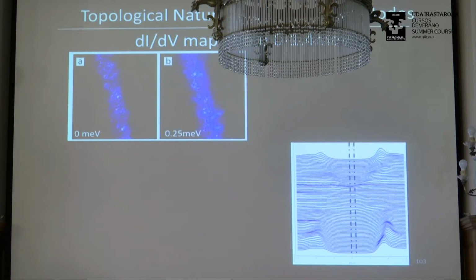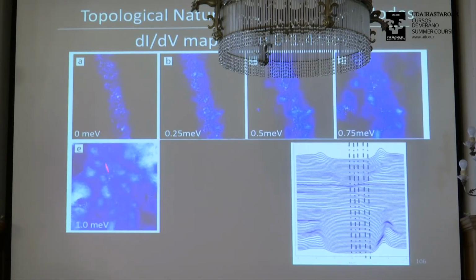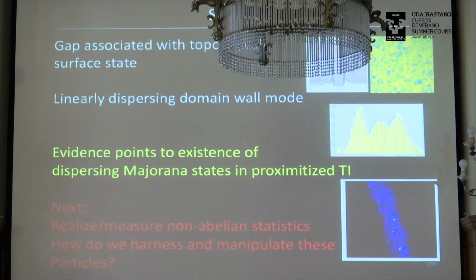However, as you increase energy, so let's say you go to 0.25 millivolts, this is 250 microvolts, the size of the spatial extent of the state actually increases. And as you go to higher energy, the spatial extent increases more. And in fact, by the time you get to 1 millivolt, which is right on the edge of the flat portion of this gap, the spatial extent has spanned the sample. So this is what you expect to see. You want this 1D state to actually connect, to span the gap, and that's what this 1D state is doing. It exists at all energies inside this gap, but its spatial extent increases as the energy increases.